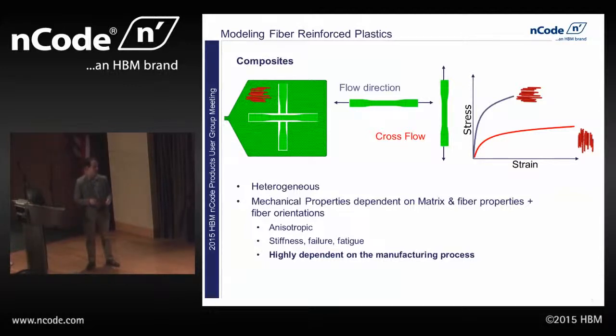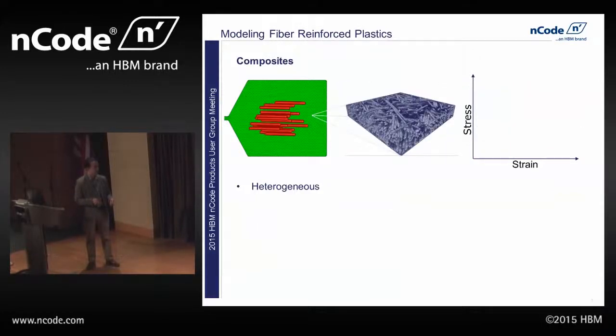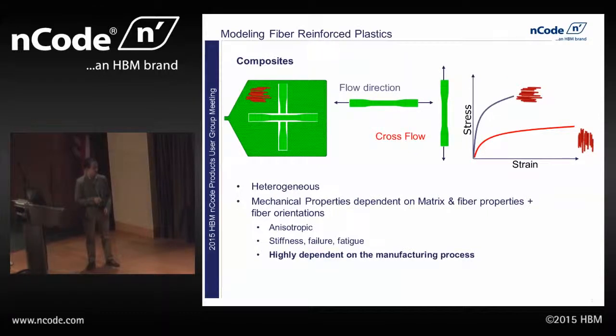Even if we start with a really basic part like a flat plate, when we injection mold that flat plate, we'll end up with a fiber orientation that's based on how that part's manufactured. In a rough way, you can say the fiber orientations align themselves in the direction of flow. If we then were to take that flat plate and test the stiffness and the strength of it in two different directions, which we could do by cutting out dumbbells in these different directions, we'd see something that looks like this.